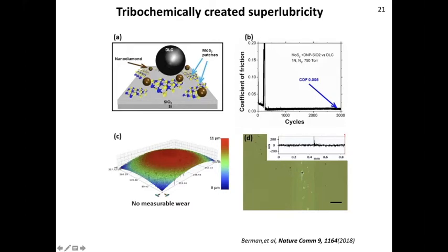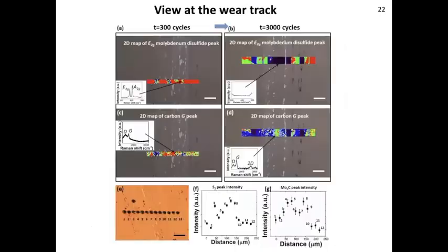And this is how the flat substrate looks. Here we see a little discoloration happening due to the rearrangement in the system. But even with this discoloration, we didn't really see much change inside the wear track in terms of the roughness profile. So it came to the question, could it be that our MoS2 works very similarly to graphene? Is it the same mechanism? We should look at this more closely to understand what is inside the wear track.